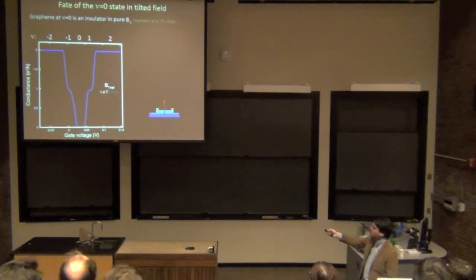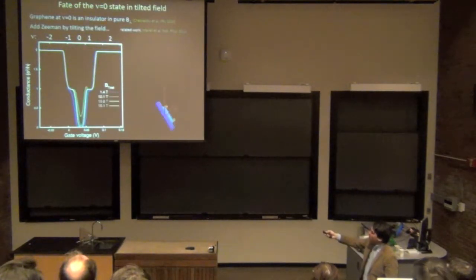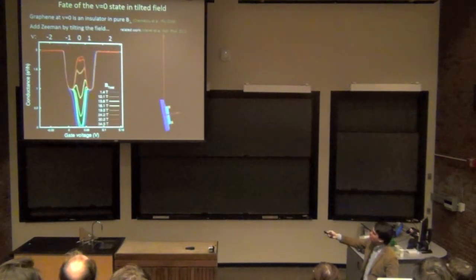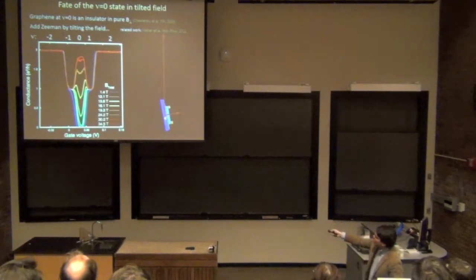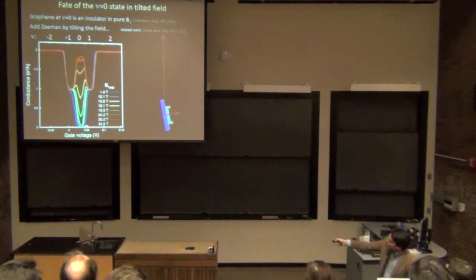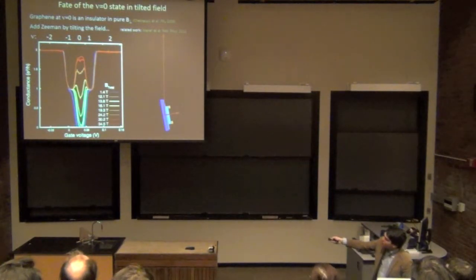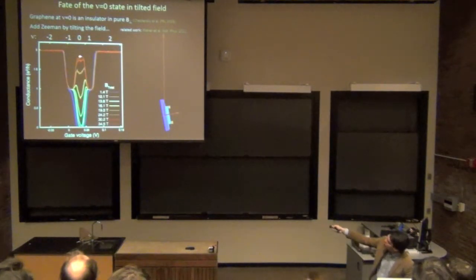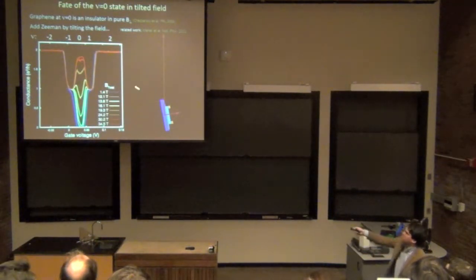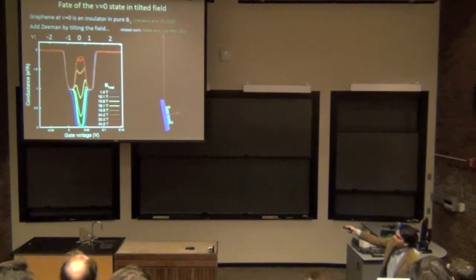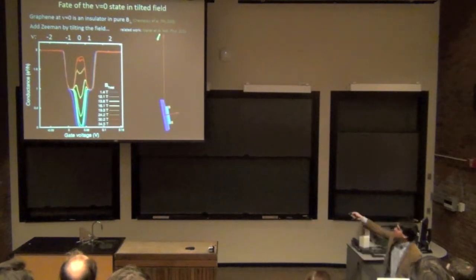So you can see what happens when we do this. Again, we took our samples to Florida. We added an immense magnetic field, and we tilted the sample at the same time. What we did was turn graphene at nu equals zero from this insulating state into this conducting state. And moreover, you can see this conducting state is very, very close to this benchmark value of 2e squared over h.